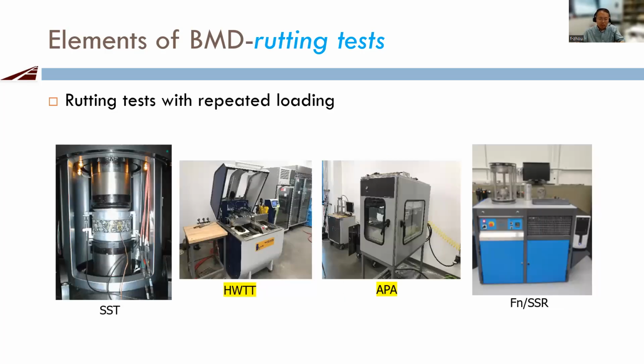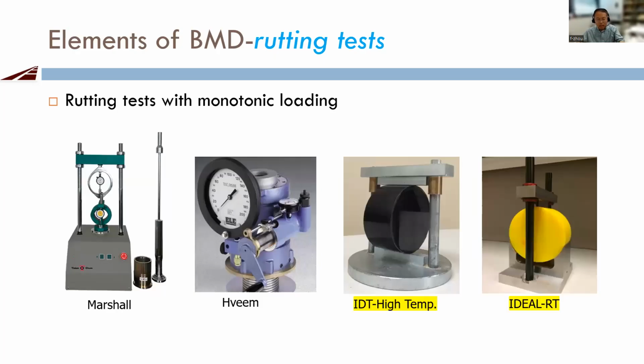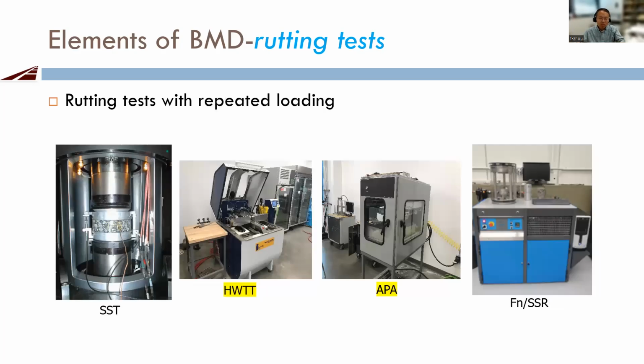And this gives you the pictures for repeated load tests. This is a simple shear test developed by UC Berkeley, Professor Carl Monismith. And this, most people use the Hamburg wheel tracking test. This is, some states use the APA. This is a flow number test. So this is the kind of rutting test. And I'm highlighting here the Hamburg wheel tracking test, APA, and the high temperature IDT, IDEAL-RT. These are the four rutting tests some states have been looking into, and some states have been using for years.